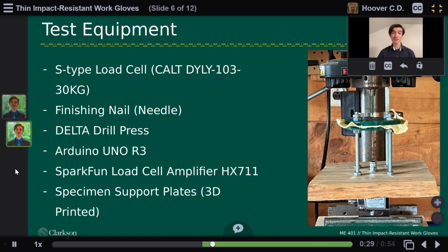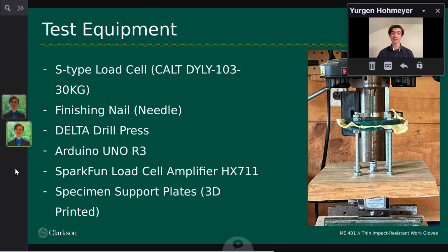To perform puncture tests on the Kevlar samples, a 30 kilogram S-type load cell manufactured by CALT was used in conjunction with a finishing nail as our puncture needle, an Arduino Uno R3 with a SparkFun load cell amplifier to capture measurements from the load cell, and a Delta drill press for vertical translation of the needle. The specimen support plates were 3D printed in PLA and secured using 1/4-inch carriage bolts.